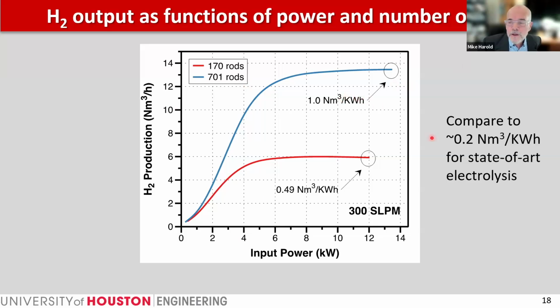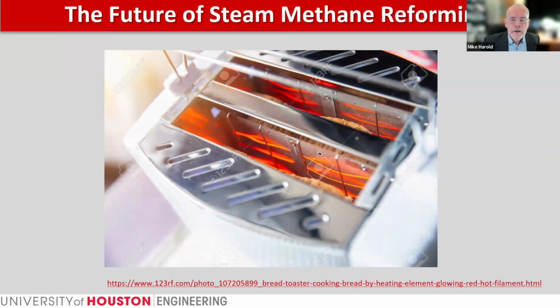It's interesting to compare that to state-of-the-art electrolysis, which is on the order more of about 0.2 cubic meters per kilowatt hour. And that's not a surprising result, but it's basically reaffirming that thermodynamically, it makes more sense to make hydrogen from methane than it does to make hydrogen from water. But it does suggest that from a scale-up standpoint that we can meet some interesting productivity levels with this kind of concept. So those are just a few of the simulations.